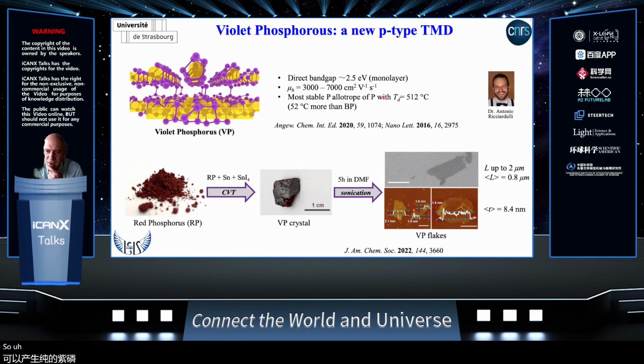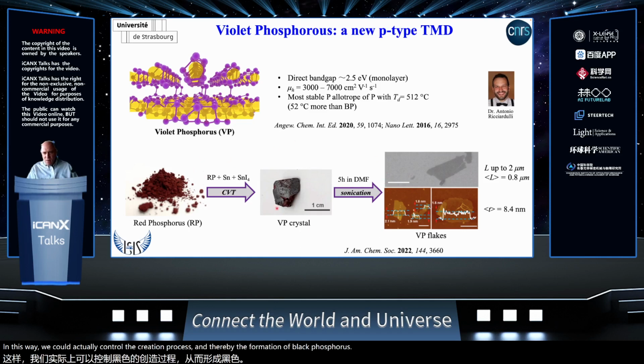So this is what we have been doing, by combining tin and tin iodide as transport agents. This way, we could control the nucleation process and avoid the formation of black phosphorus. Once we had created this kind of crystal, with a size on the centimeter scale, we exfoliated it in DMF. You can see here the flakes by electron microscopy and by AFM. The lateral size of the flakes can go up to 2 micrometers, and the average thickness is about 8 nanometers, so a few layers thick.